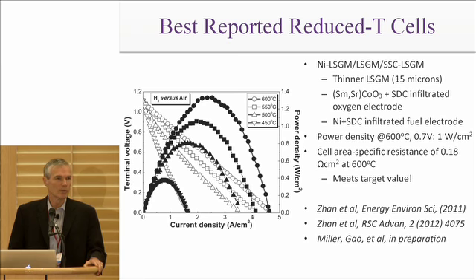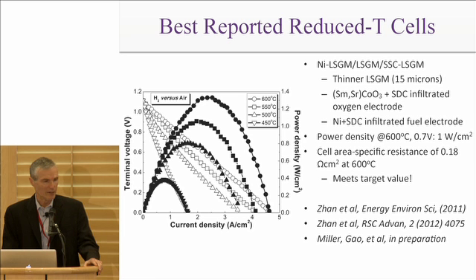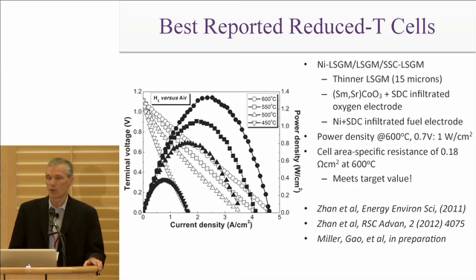And it turns out that some of these devices have actually produced what we think are some of the best reported power densities as fuel cells that have ever been reported for devices operating less than 600 degrees centigrade. And this is just showing one of the results that we published recently on this, showing power densities well in excess of 1 watt per square centimeter at well below 600 degrees centigrade, which is a pretty remarkable result.